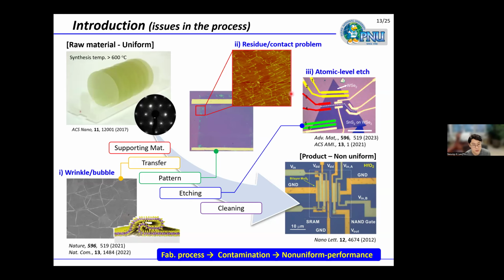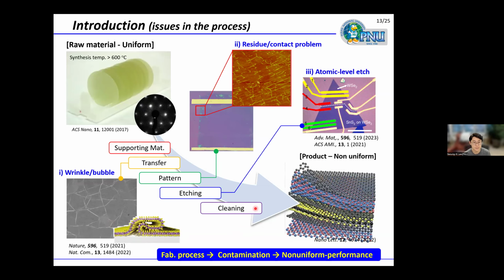These residues lead to unstable contact with the subsequent layer. To mitigate this, additional thermal treatment and cleaning processes are often applied. However, such treatments can damage other components on the device. So devices frequently exhibit non-uniform performance due to residue contamination and unintended doping effects. These issues become even more critical in heterojunction structures, where multiple layers should be integrated on an edge like this kind of image.